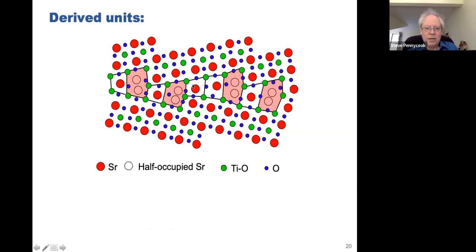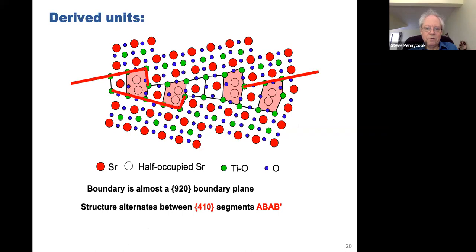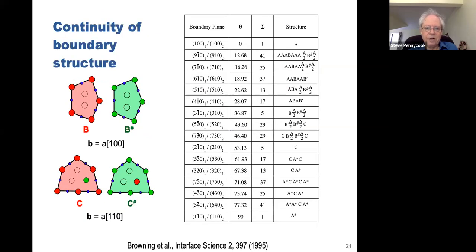But it's quite easy to see how the grain boundary is built. This was a 920 grain boundary plane. And you can see it was basically built with these structural units, these sort of double columns, very closely spaced, and made of segments, 410 and 510. And you just put in an extra spacer unit here, highly distorted, but just separate out these dislocation cores, and you can build the boundary at whatever angle you like. At larger angles, you would come to need 110 type dislocation cores, this kind of structural unit. But essentially, this rather nicely proves the continuity of boundary structure.